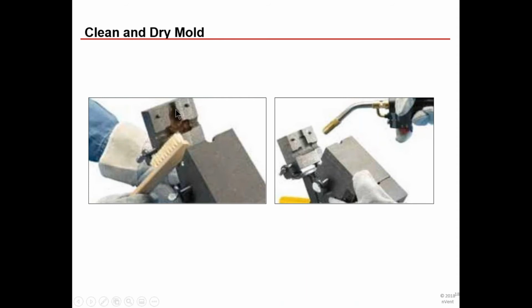You then want to make sure that you thoroughly clean your mold. It needs to be clean. A dirty mold can attribute to damage or poor construction of the mold. You also, and this is one of the safety features, need to blowtorch the mold. These are graphite. Graphite sucks in moisture. If you have moisture in here, when it heats up, it can super expand. And you could have something where you have a blowout of one of these holes. At the least, you could end up with a poor quality mold. On the safety side, it could cause a safety issue.